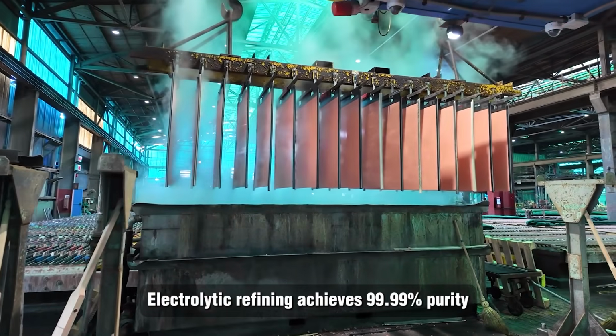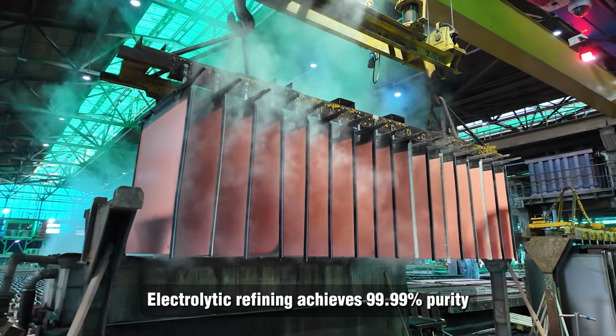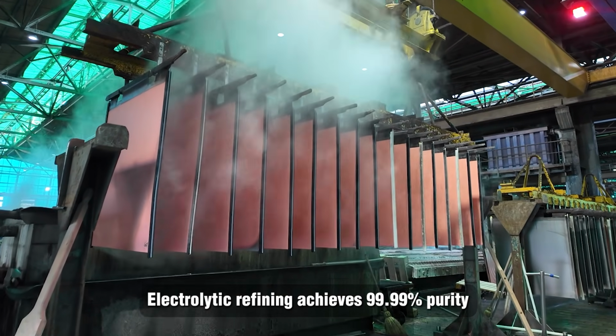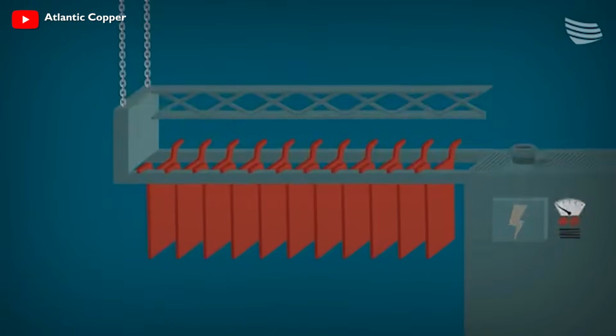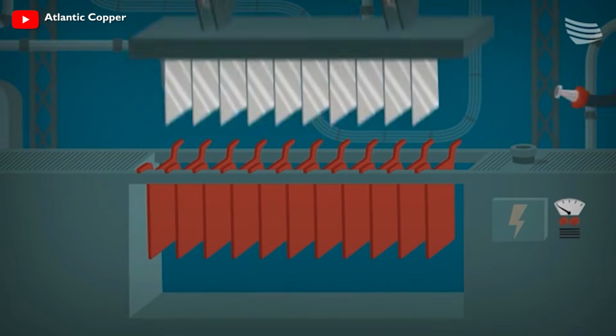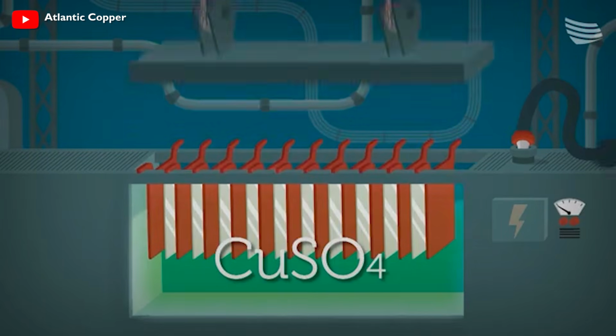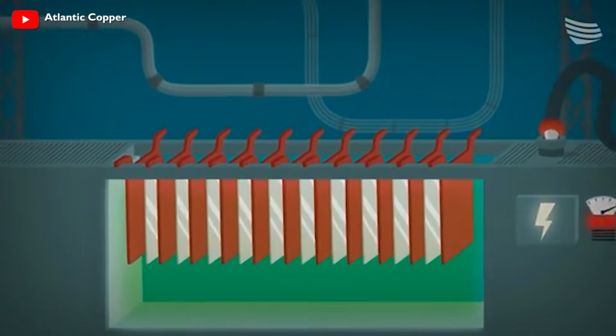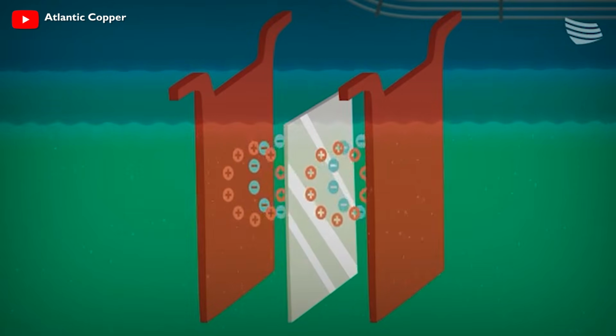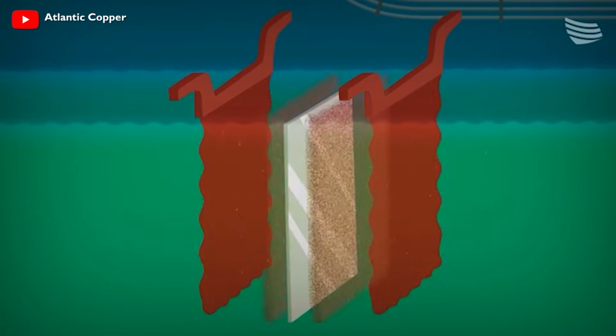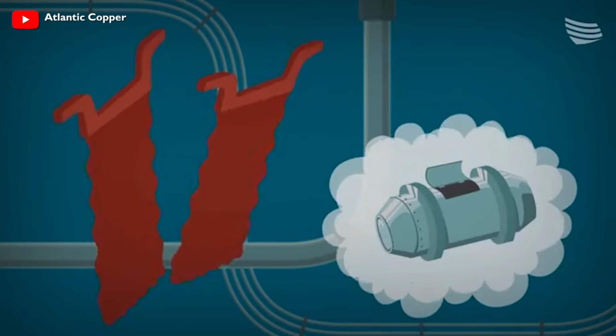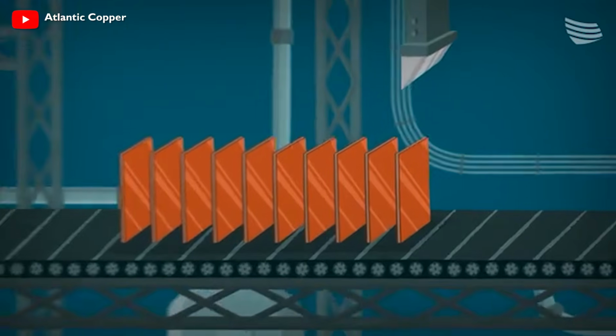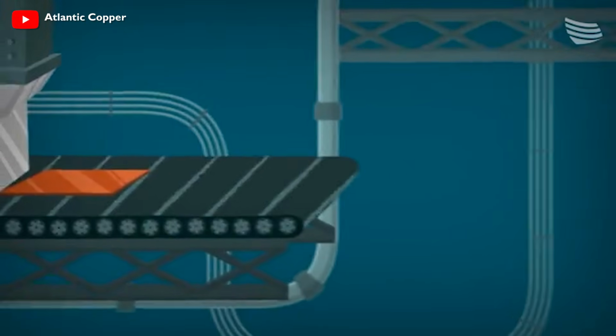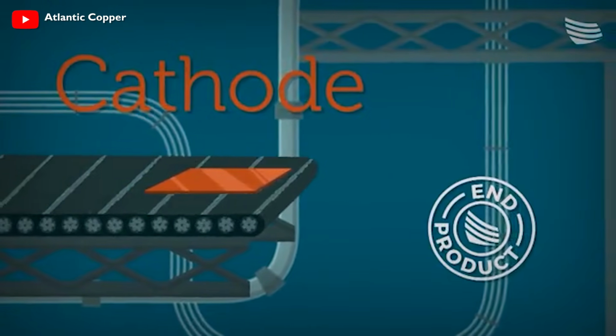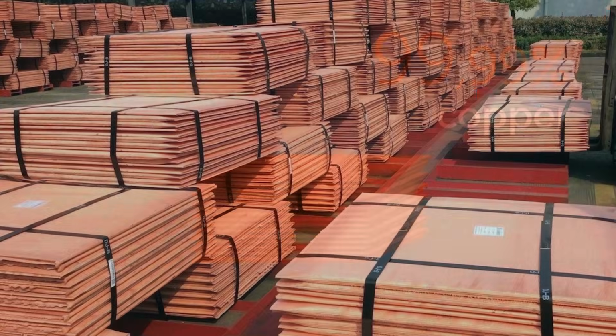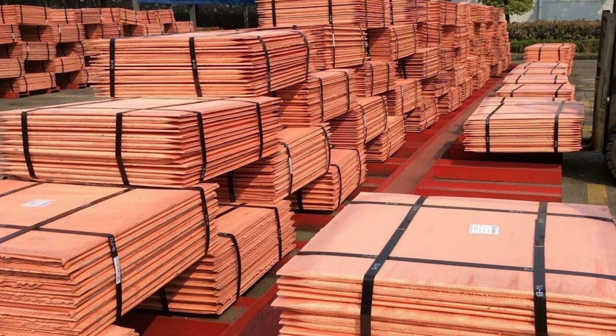The final purification employs electrolytic refining, achieving copper purity exceeding 99.99%. Large slabs of blister copper serve as anodes in electrolytic cells containing copper sulfate solution. When electrical current passes through, copper atoms dissolve from the anode and deposit with extraordinary purity onto cathode sheets. After approximately 2 weeks, the cathodes achieve their full thickness of 100 to 150 kilograms of ultra-pure copper, the starting material for all copper wire production.